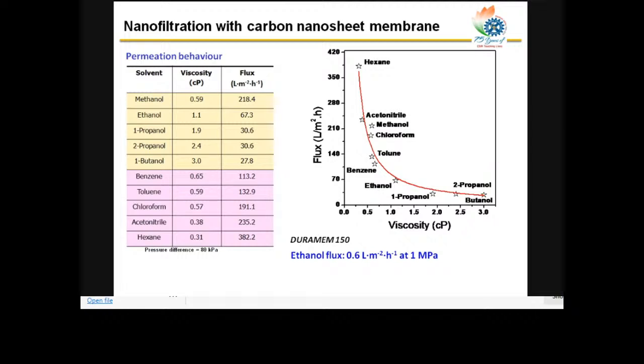we established for the first time that a very small pore, less than a nanometer, is actually showing a viscosity-dependent relationship of the permeability. So the solvent can go through, even a viscous liquid, and the flux of this liquid, that means how fast the solvent is going through the membrane, is basically 100 to 1000 times faster than the commercial membrane. So in a nutshell, what we have made is a carbon thin film which is porous and has a definite pore size of less than 1 nanometer, and it also allows viscosity-dependent solvent flow through the membrane, and is 100 to 1000 times faster than the commercial membrane.